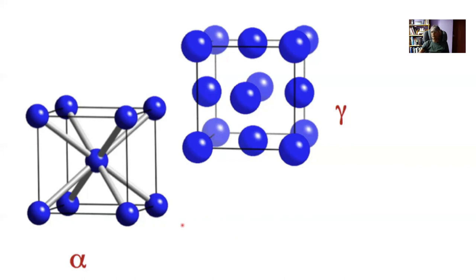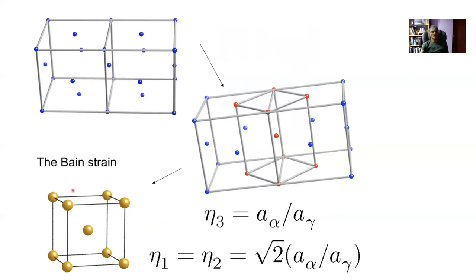How do I deform homogeneously the lattice of the austenite into that of the ferrite or martensite? Well, Bain came up with this in 1924. If you draw two unit cells of austenite together, you can identify a different atomic arrangement which is a body-centered tetragonal austenite. We've done no transformation yet — this is simply a relabeling of the unit cell, because there are many ways in which we can draw the unit cell.